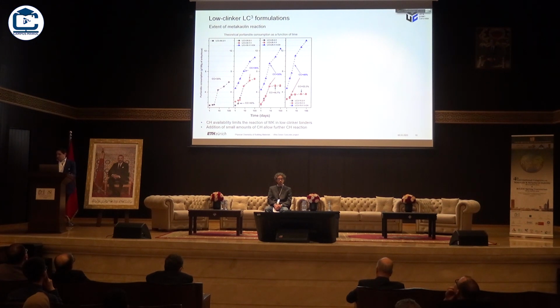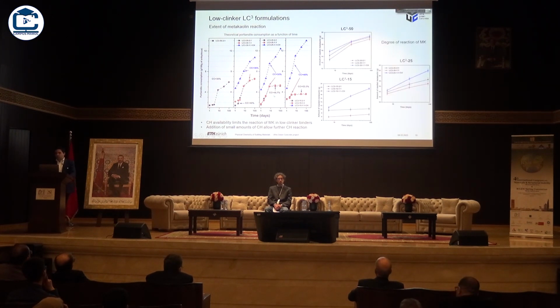So then, an idea could be: what happens if we add a small amount of Portlandite in order to boost back the reaction of metakaolin in this low clinker system? And this is basically the blue line that you see here, where you see that we can completely increase the amount of reaction that we have, which is also reflected in the evolution of the degree of reaction of metakaolin in these systems.